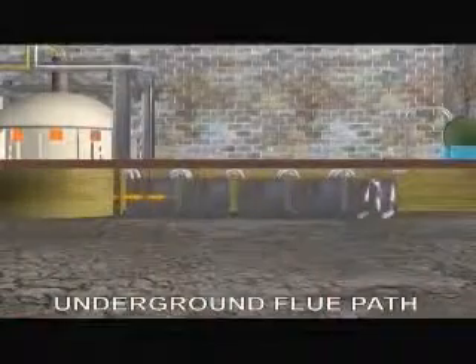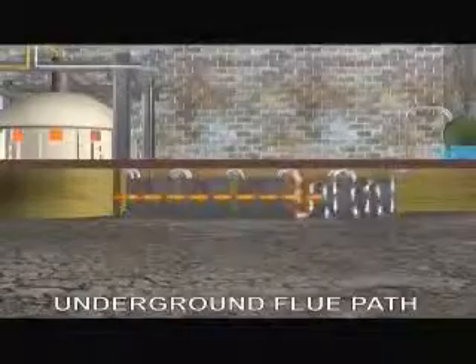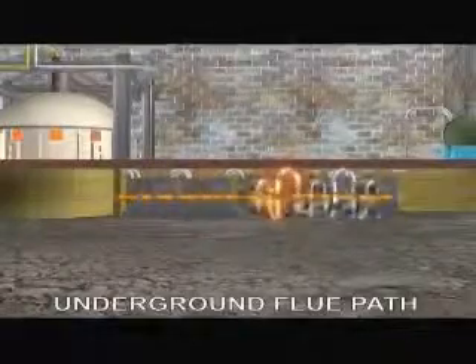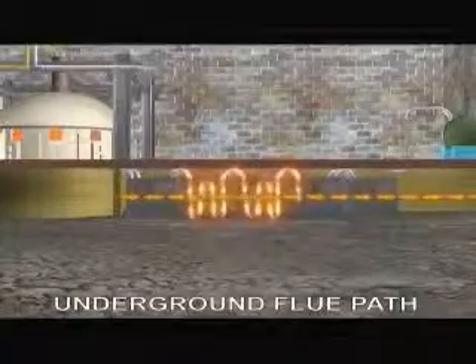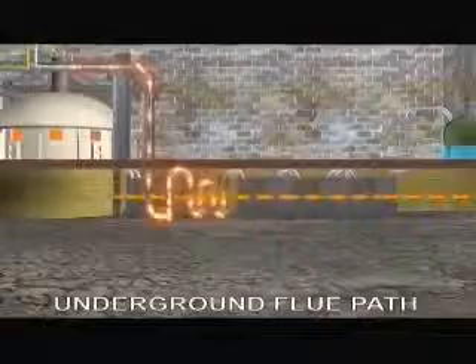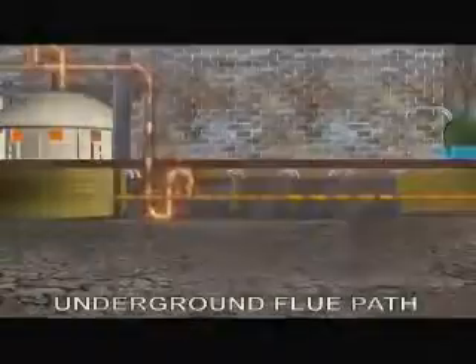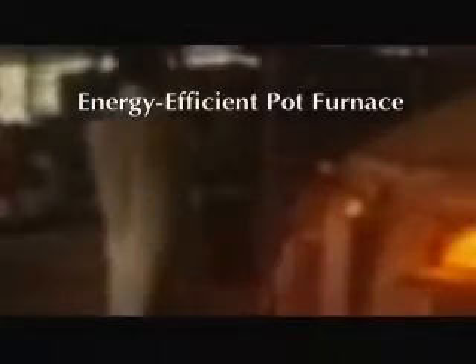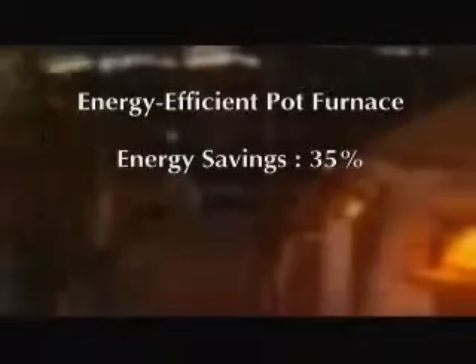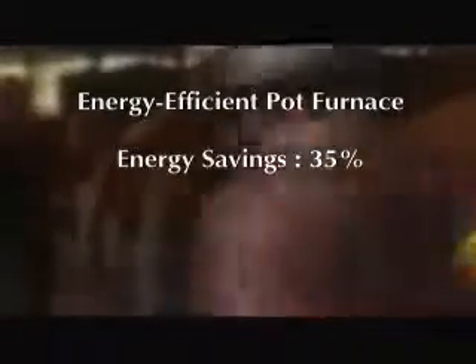Before the flue gas reaches the chimney, it passes through a heat recovery system called a recuperator. Using this device, the hot flue gases raise the temperature of incoming combustion air substantially, from 40 degrees Celsius to 500 degrees Celsius. Thus, the amount of energy usually required to attain this temperature is saved. As a result of the sound technology, the furnace consumes nearly 35% lesser energy than the conventional gas-fired furnaces.